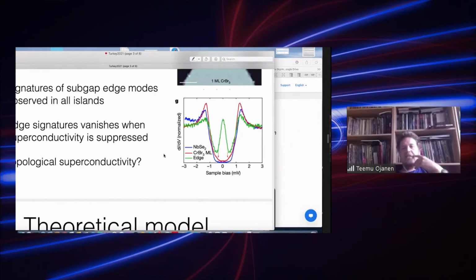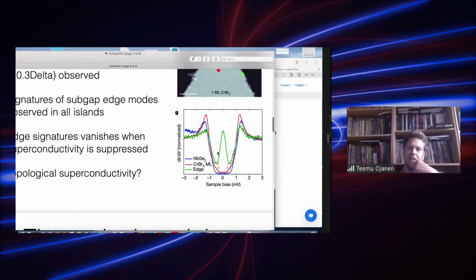Okay. This is a question which is asked quite a lot. If we have a density of states, it would be almost constant inside the mini-gap. That's what you would expect. But here we should understand that this dI/dV is the local density of states, which combines two features. It reflects the density of states and the wave functions. And this means that the fact that this looks like a zero bias peak, even though there are dispersive modes, just means that...